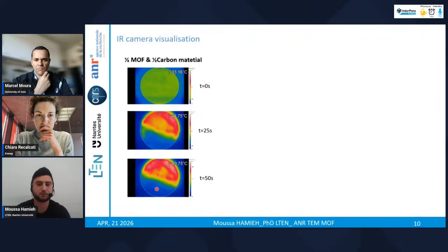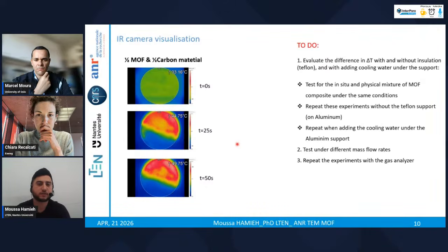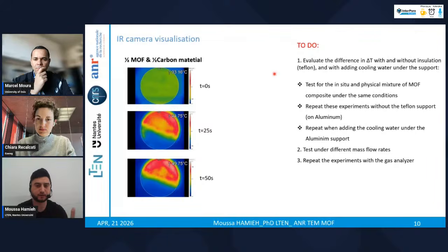As a plan for this experimental setup, we will compare the pure MOF and different compositions of the carbon in the composites. We will compare between the Teflon and the aluminum, as I said, with insulation and without insulation. We will compare the behavior when adding the cooling water under the support of aluminum also, and we will check for different mass flow rates. At the end, we will repeat all the experiments when we receive the gas analyzer to correlate the results and understand better what happens in each case.